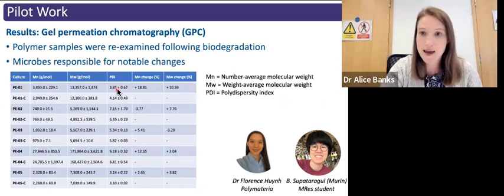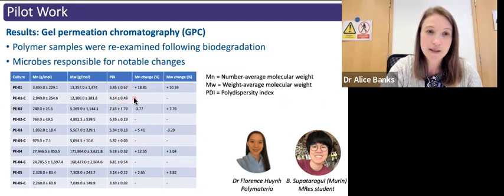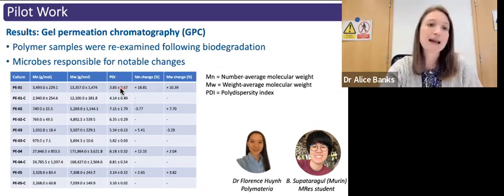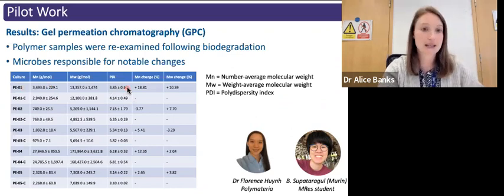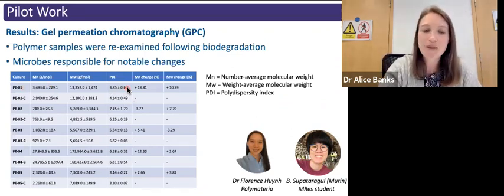Then the PDI index in the experimental sample is lower than in the control. So this may suggest that many of the particles available of one particular size have been consumed, and this has left some that are less accessible to the microbes.